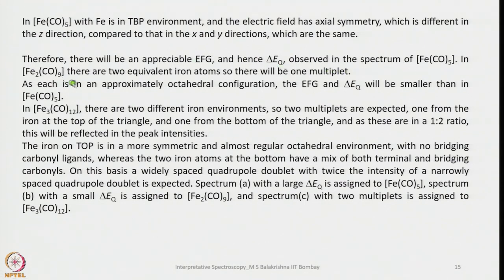In Fe2CO9, there are two equivalent iron atoms, so there will be one multiplet here. And as each is in an approximately octahedral configuration, the EFG, and hence delta EQ, will be smaller than in FeCO5. And in the case of Fe3CO12, there are two different iron environments that can be clearly seen from the structure. So two multiplets are expected, one from the iron at the top of the triangle and one from the bottom of the triangle.